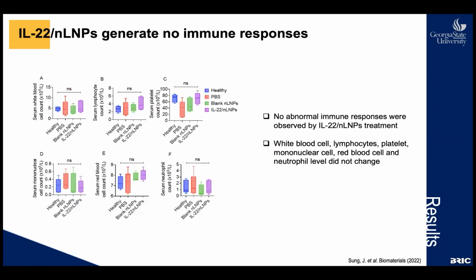To confirm any immunological responses after treatment, we collected serum samples from each group and counted blood cell levels, including white blood cell, lymphocyte, platelets, mononuclear cells, red blood cells, and neutrophil cells. And there were no significant differences between the groups, meaning that there were no abnormal immune responses observed from the treatment of the IL-22 lipid nanoparticles.